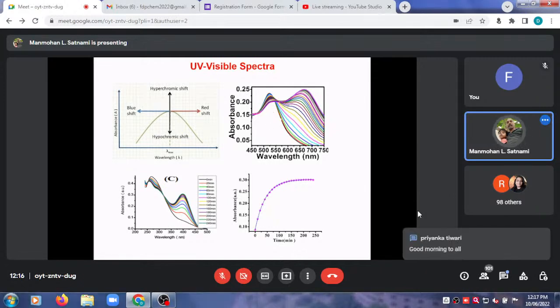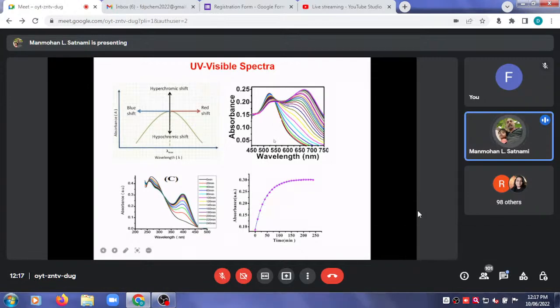Understand? And see, if we put a very little amount of any compound and take the absorbance of that molecule, it will give you absorbance at maybe 0.1. And if we increase the concentration, then absorbance will increase. There will be a hyperchromic shift. And in between these two peaks, at 520 and 655, when the absorbance at 520 is decreasing and 655 is increasing,